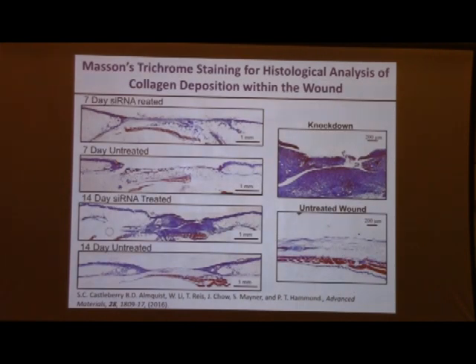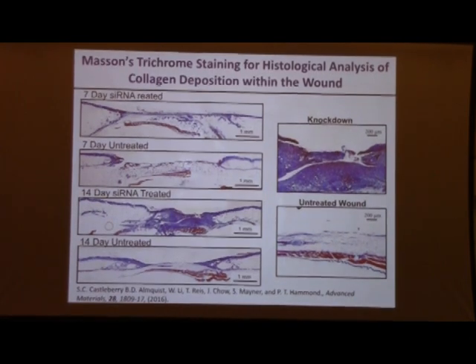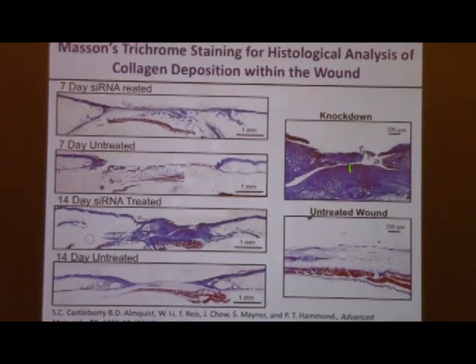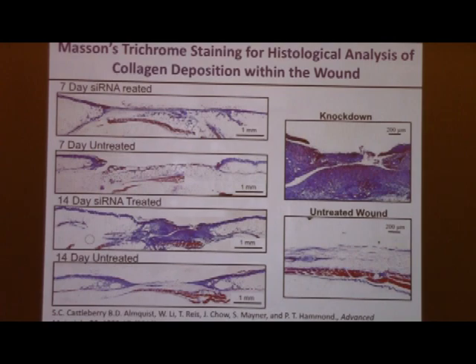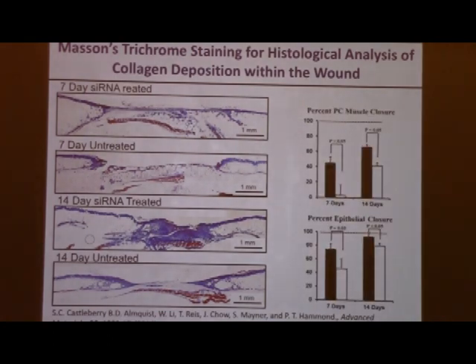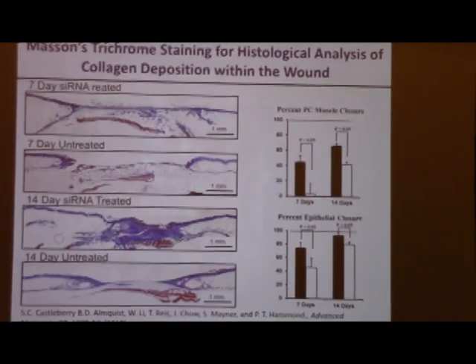Because it's sustained over time, it allows us to see this gradual generation of collagen in the wound cavity. In this case, collagen is seen as blue. And you can see the 7-day treated and untreated, and you can see the margins of the wound here and here. In the untreated, you don't really see this nice blue line of collagen deposition. But you do see that it's being formed here at the treated site. At 14 days, there's a more dramatic difference between the treated and the untreated wound. And you can see a blow-up of this tissue here, very nice granulation tissue that is now ready to undergo that next step of remodeling. So we're excited about these results, and we're looking at how we might be able to further advance them. And we can also see rates of increase in wound closure in these animals.